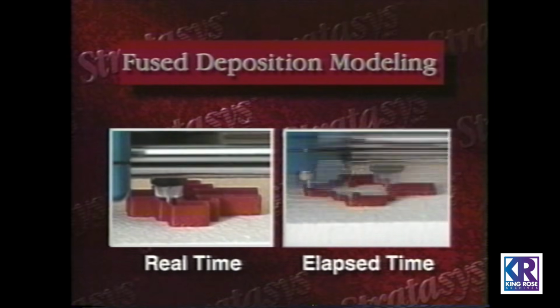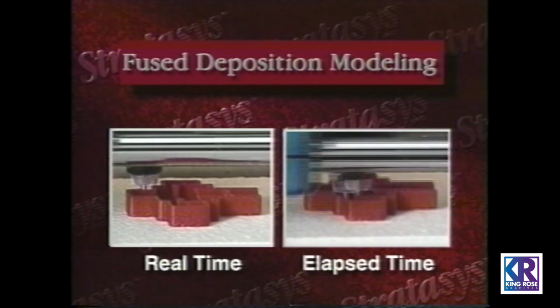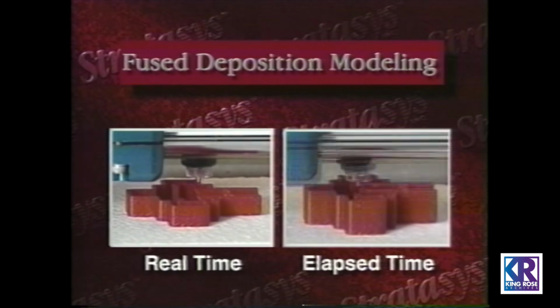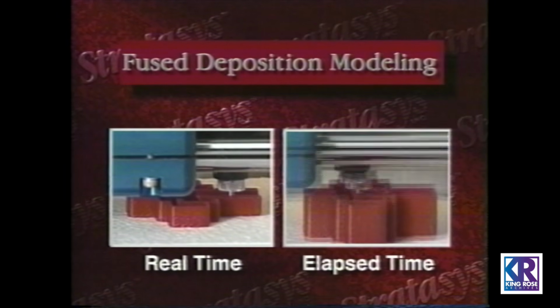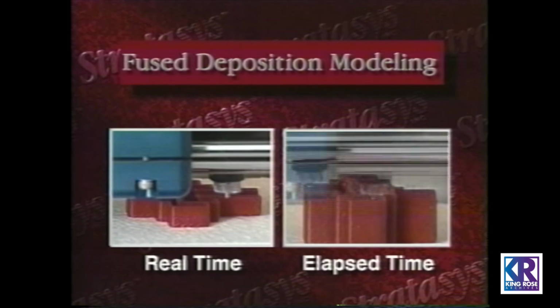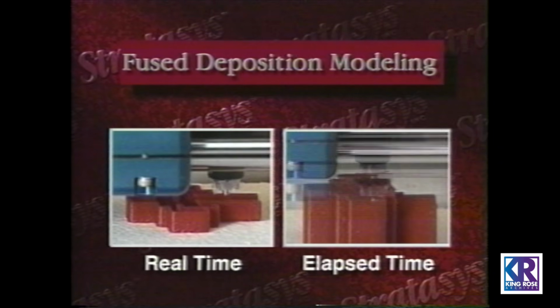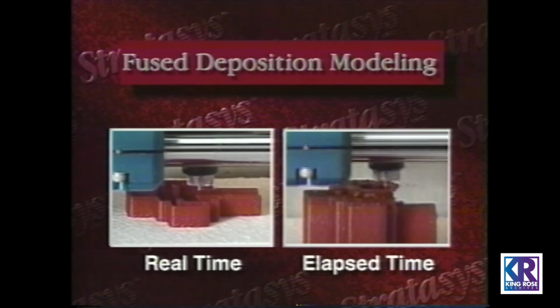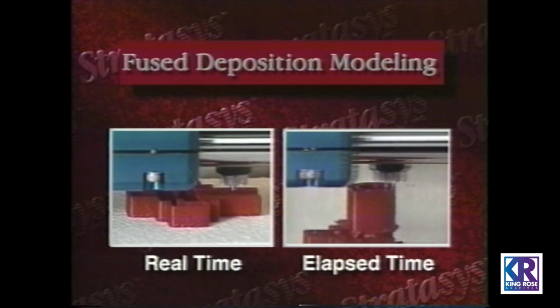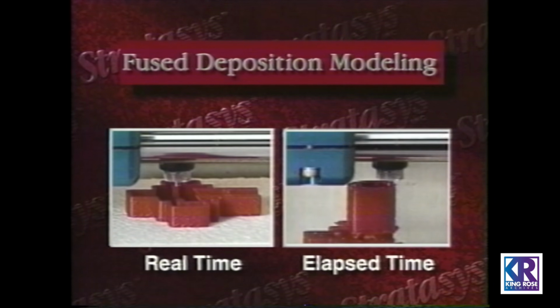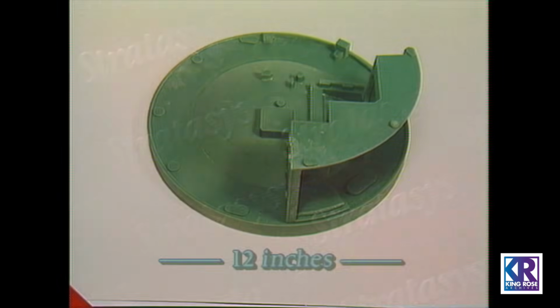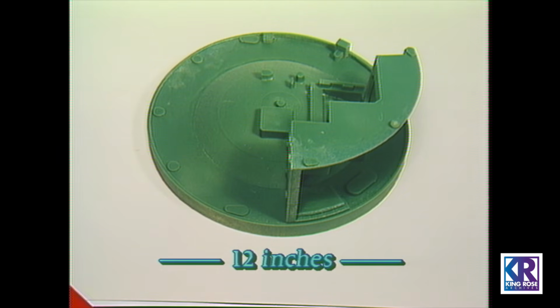Since it is only slightly above the melting temperature, the wax quickly solidifies after joining to the underlying layer. When a layer is completed, the supporting table lowers and the process continues with the next slice. After the final layer is deposited, the part is removed from the table. The fused deposition modeling process is already being incorporated into Sandia's production of prototypical components. This wax pattern was produced entirely from an electronic design.